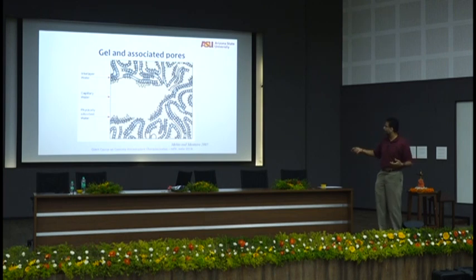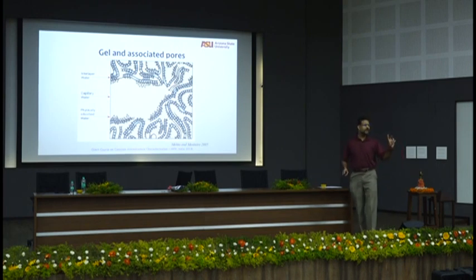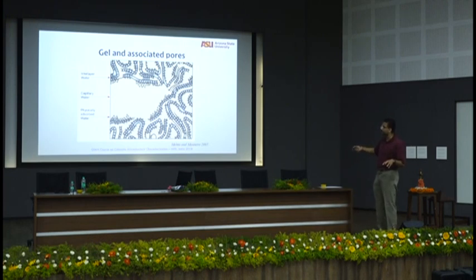So some people will talk about, oh, removing gel water. I'm not a big fan of talking about removing gel water, because if you remove gel water, you don't even have the thing in the primary place. So yeah, you can remove capillary water, you can remove adsorbed water, you can rearrange gel water. So gel water changes, like I said, because this capillary water is gone, you have internal rearrangement. So gel water rearrangement happens, gel water doesn't go away, should not go away.